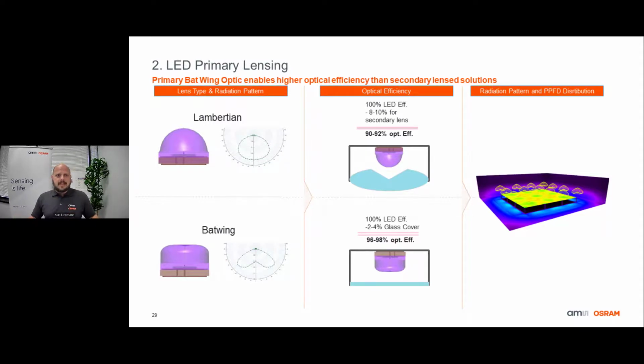So here we can see the comparison of the two methods of creating a batwing distribution that I mentioned earlier. On the top, we can start with a traditional Lambertian LED. We can then place a secondary optic over this LED. Now, adding a secondary optic not only adds cost, but it will add additional optical losses. A secondary optic could lead to anywhere between an 8 to 10% reduction in photon flux.